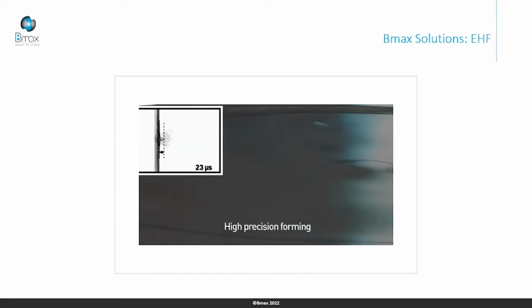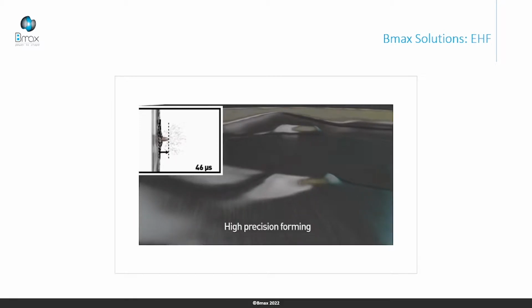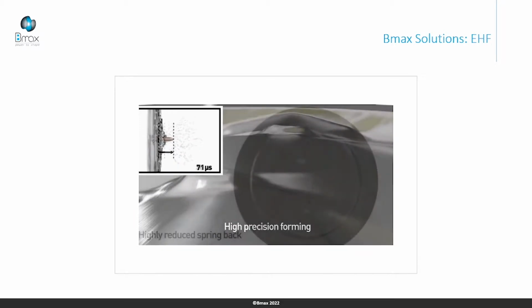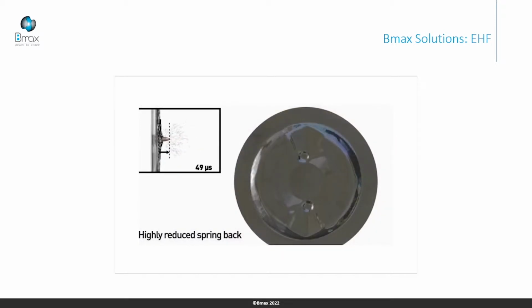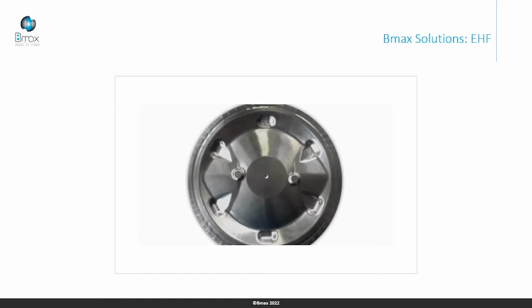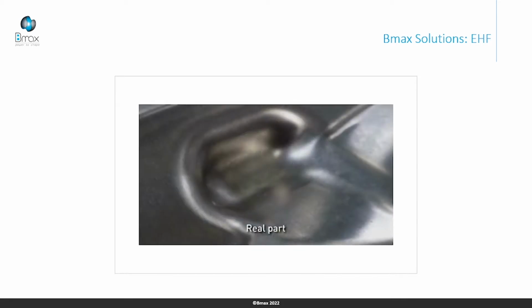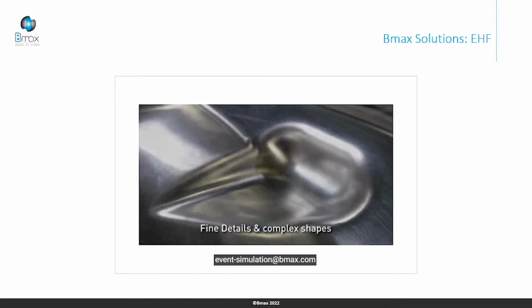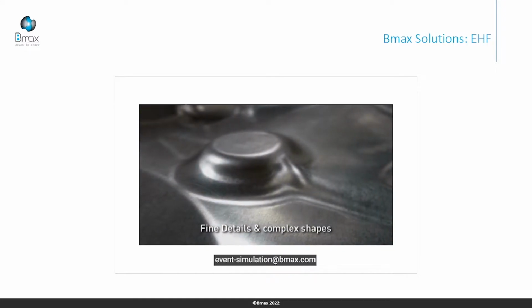We have an excellent thickness distribution. We have no issue, no defect due to the springback, and we respect all the geometrical tolerances for this product. And we have a very good compliance between numerical results and experimental ones. If you want further information about this case study, feel free to contact us.